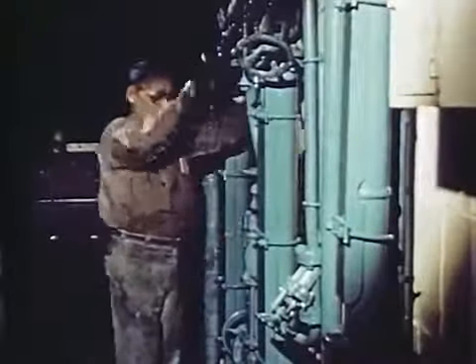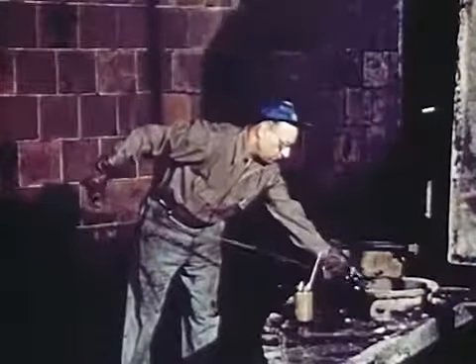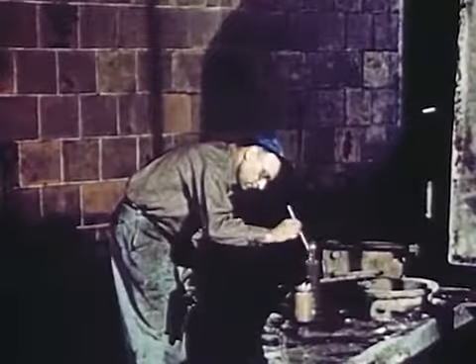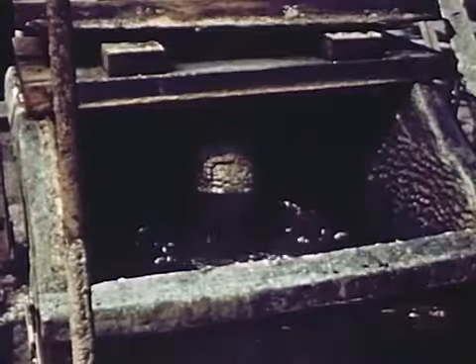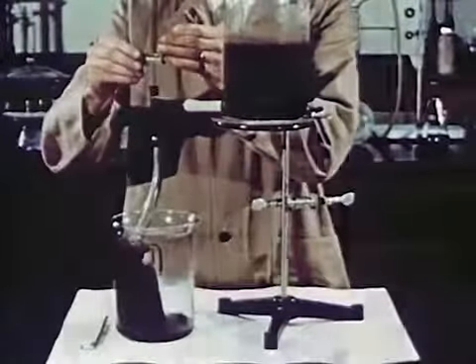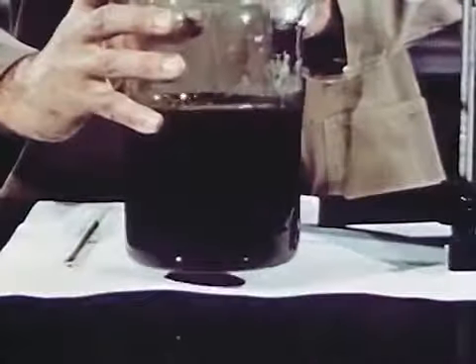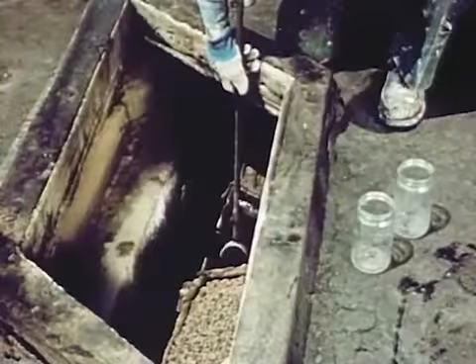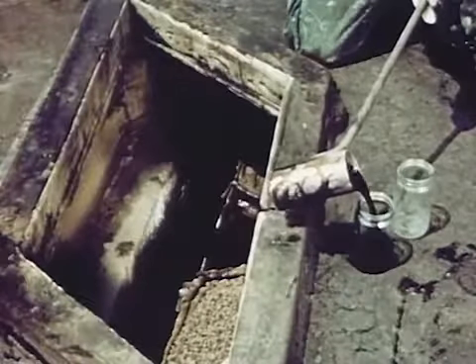Throughout, the specific gravity, acid strength, and temperatures must be regulated, and the solution analyzed to note what is happening to the titanium, iron, and sulfuric acid. The digestion process leaves the solution with a suspension of muddy residue. The solution is then clarified by settling out the insoluble ore which sinks to the bottom of the tank. This residue is washed for maximum recovery of the solution. The clear solution overflows from the settling tanks and is then filtered to remove any further traces of insoluble ore.